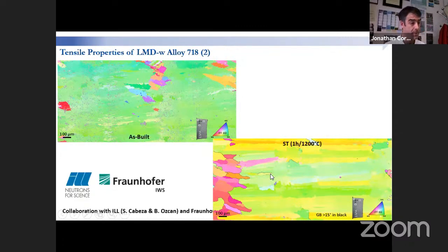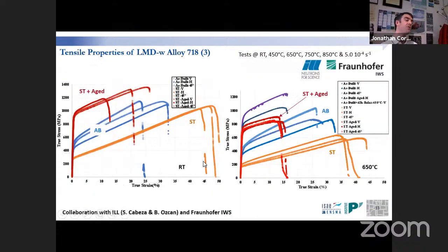And when we do further solution treatment, we can see an even greater texture. I'm not showing here the texture map from which we could understand the texture better, but that's very obvious from the EBSD map. With this, we have been doing tensile tests along the horizontal direction, the vertical direction, so the build direction, and also at 45 degrees. That's what I'm showing here. All the tensile tests have been done at the same strain rate, 5×10⁻⁴ per second, at room temperature, 450, 650, 750, 850. I will first start with the room temperature test.